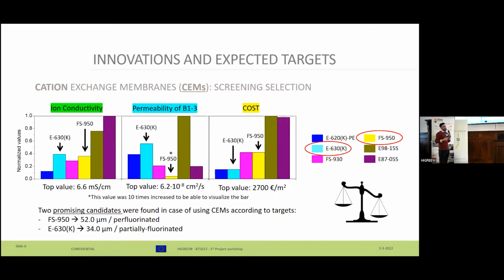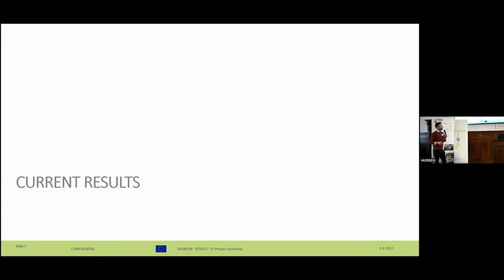In the case of cation exchange membranes, the selection was performed in the same way, but it was a bit more difficult because we had to deal with more than 3 membranes, at least 6. So the promising candidates were the FS950 and E-630(K), although we also considered the FS930 because it's the same material, but in its thinnest version. Both are also from Fumatech. The first one is perfluorinated and the other one is partially fluorinated, according to the chemical composition that we have seen in our infrared spectra.